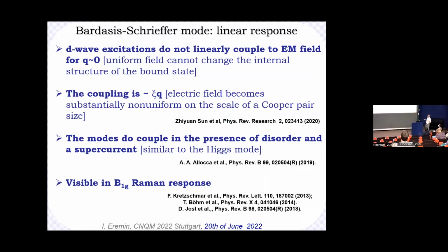Okay, so this is something that got quite an interest also in the linear response, especially in the context of the iron-based superconductors, where such a Bardasis-Schrieffer mode has been applied. So this is a summary of what is known so far. What you see in the linear response is basically an excitation which is D wave in the S wave ground state. You cannot excite it at Q equal to 0, but as soon as you have a finite Q, you can generate it. And what is most important is that it's visible in the B1g response.